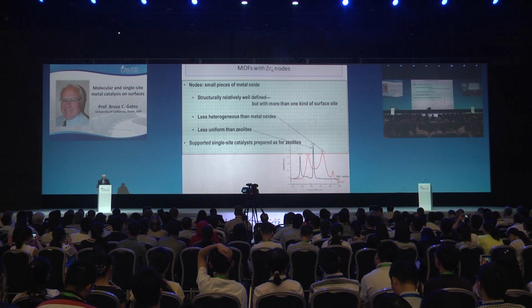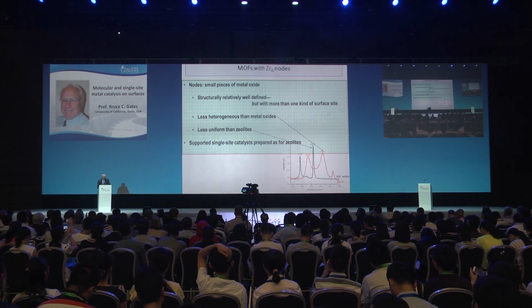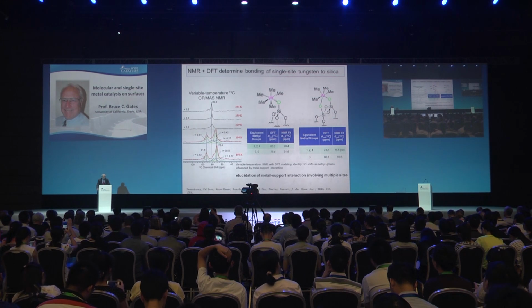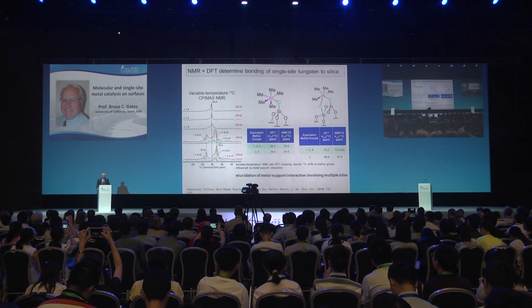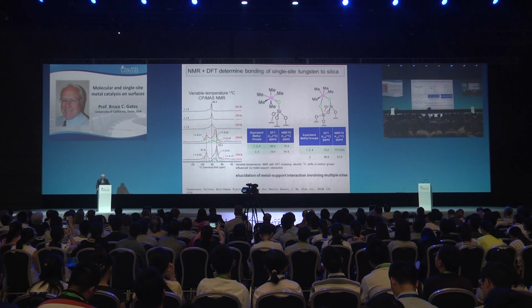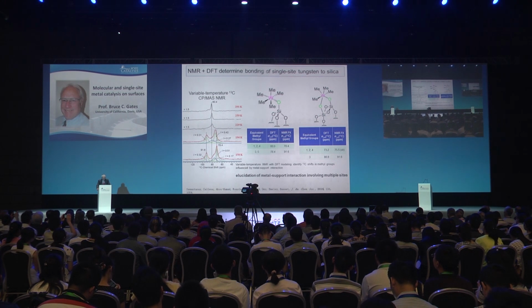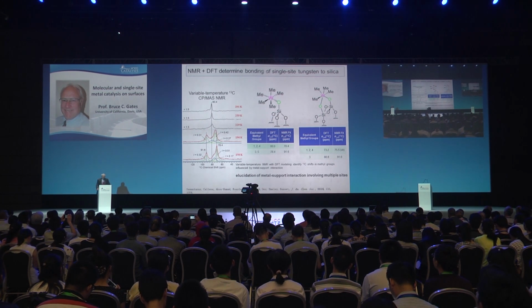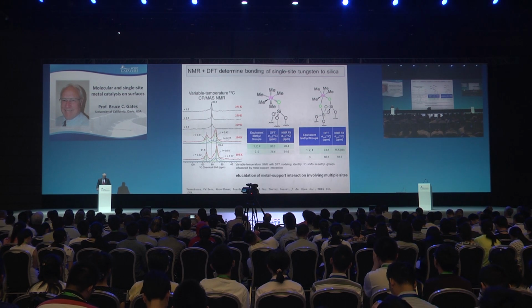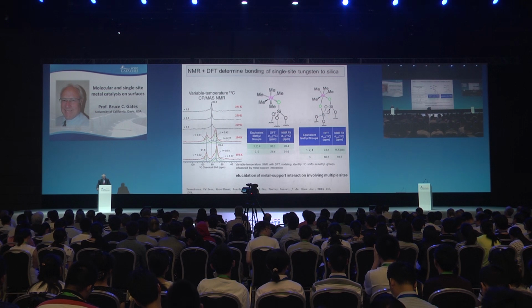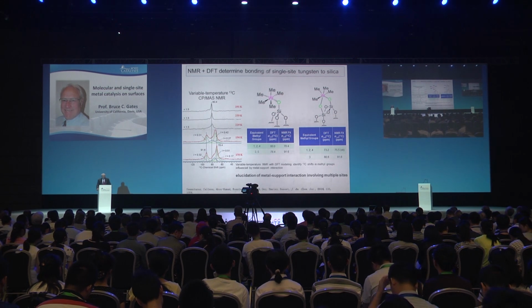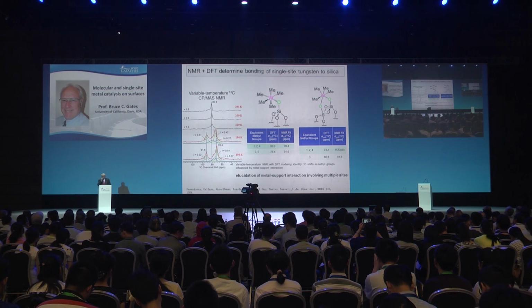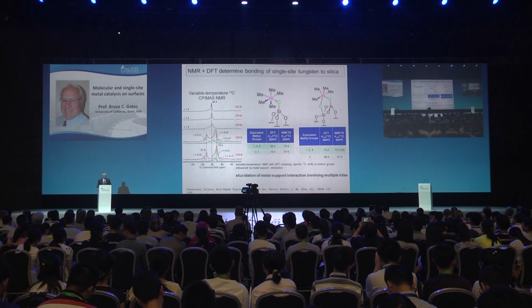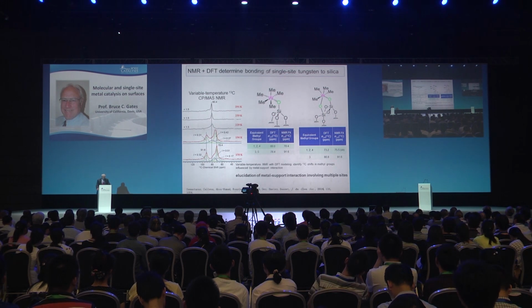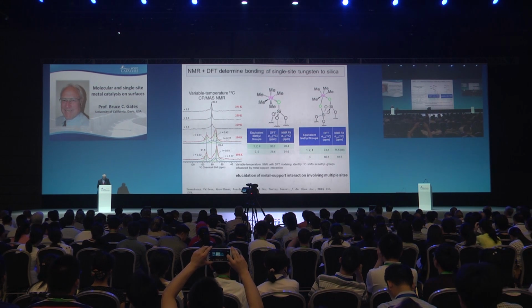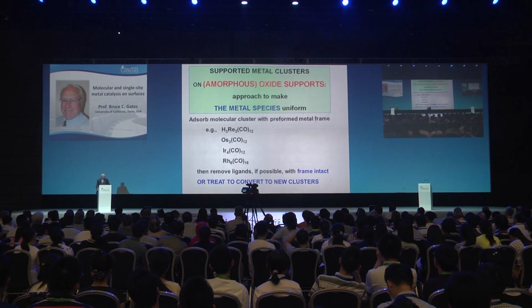So they start suggesting what goes on amorphous surfaces. There's an enormous and beautiful literature of metal complexes on silica. I show one example from the Basset group, in which they show the power of NMR spectroscopy for elucidating structures. So you see a monopodal tungsten complex and a dipodal tungsten complex, inferred from DFT combined with NMR spectroscopy. So the complexity of the amorphous materials is greater than that of the zeolites, for example, but one can deal with that, and there are lots of opportunities to get even more precise there.